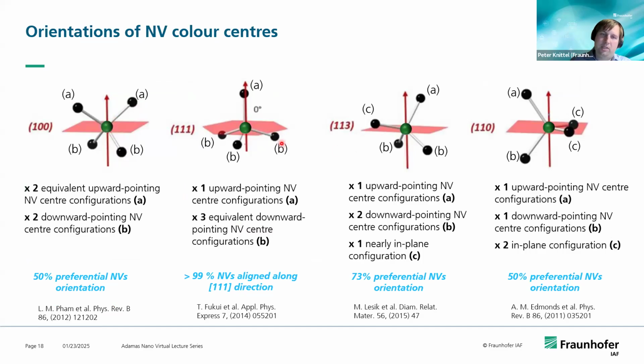And if you use a 1-1-1 oriented diamond crystal, you may even achieve almost 100% alignment of NV centers that are formed by growth in the surface, normal being one of the 1-1-1 directions pointing upwards in this case. So it has been shown in recent publications also that this is possible for 1-1-3 and 1-1-0, but the highest orientation is achieved with these 1-1-1 diamonds, and that's something we also do.